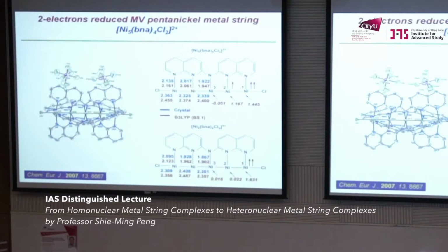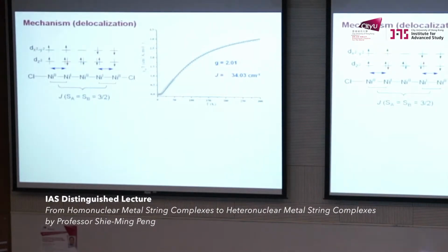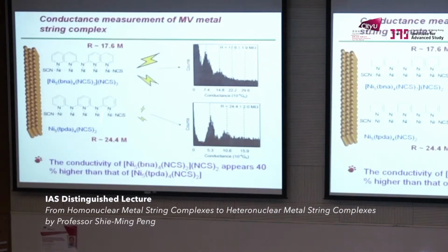Because this has only one anion, previously you have dianion, and the spin state is 1,0,0,0,1. But this can be easily reduced by 2 electrons to get the nickel 1 in the inner positions. And when you have nickel 1, very easily, the last electron will go to dx squared minus y squared, which is metal-ligand antibonding. So you can see the metal-nitrogen distance become longer. Okay, so we can study all the magnetic properties. This antiferromagnetic center is coupled more strongly with another one, much stronger than the previous pentanickel system. And the most important thing is that the conductance increased 40% by introducing this mixed